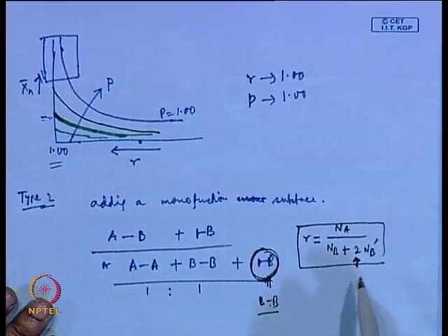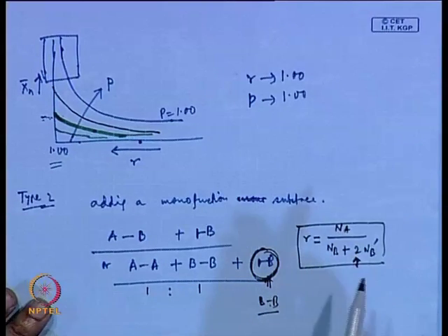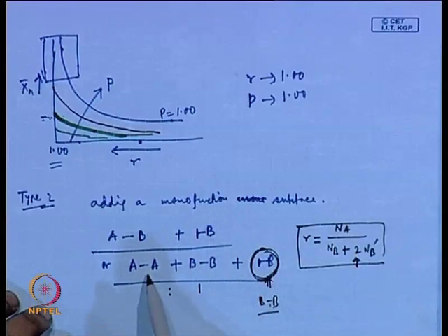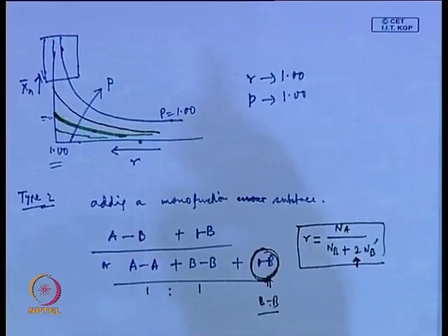Now, what is the advantage of this monofunctional group? If you remember, using a monofunctional group the ends are capped with non-functional groups, whereas in the type 1 strategy where one of the groups is in excess, you still have virtually dead polymer, but with the same functional group present on both sides. They do not react with each other, but you still have functional groups.